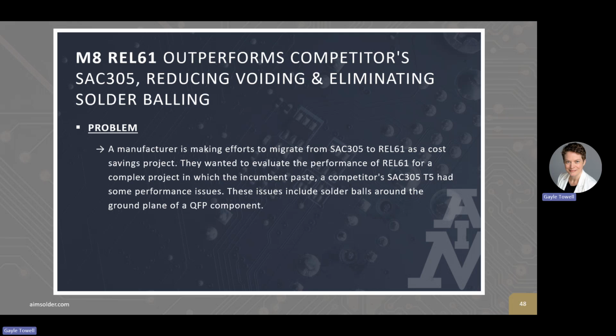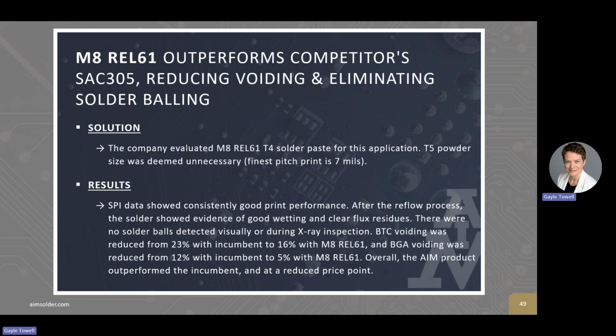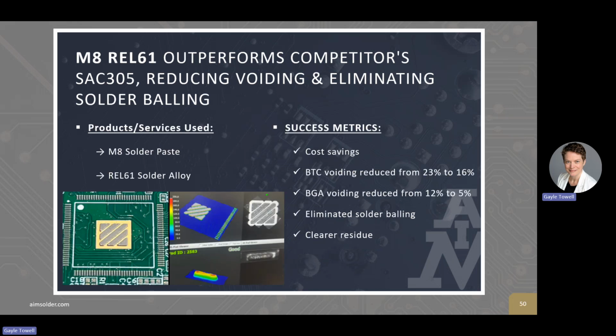They wanted to evaluate the performance in a complex project in which the incumbent paste had some issues. And these issues included, again, solder balls on the ground plane of a QFP component. They tried out REL61, and they had very good results with their voiding. The end result was they were able to save costs. They reduced their BTC voiding from 23% down to 16%, BGAs from 12% down to 5%. The solder balling issue was eliminated, and the residues were clearer in appearance.